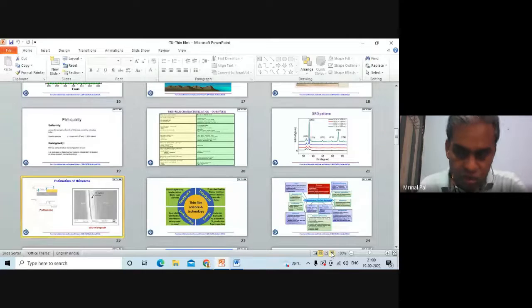For example, when I was a student, research scholar, GRF, SRF, I worked on some thin films prepared by a chemical process. Our target was not exactly application of that process to any sophisticated device. Our target was to make some non-conventional films and to characterize them electrically. In that case, we used glass slides as substrate, and before depositing the thin film, we used to keep the glass slides in HF solution. HF has the property to degrade glass. Glass is almost a non-degradable material. Years after years, more than 100 years, it can stay. But the most easy way to degrade glass is to use HF.